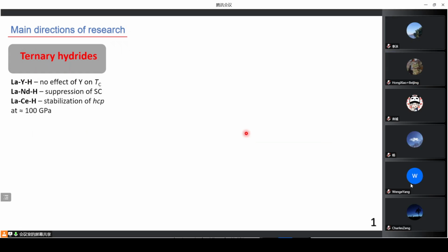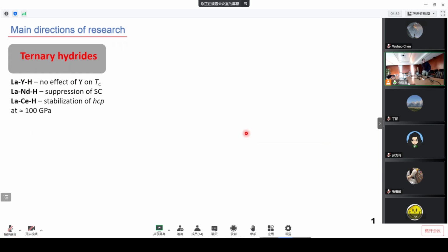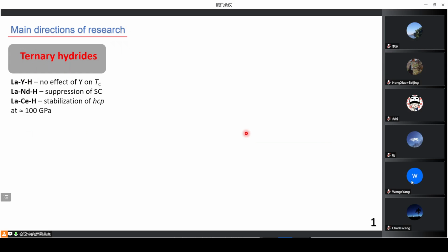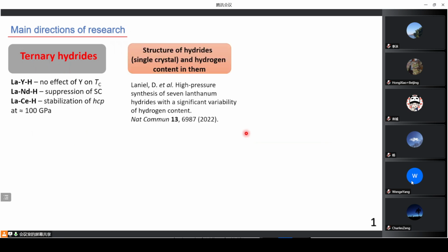And in the last system, lanthanum-cerium hydrides, my colleagues from Jilin University found that we can get some benefit in stabilization pressure. Stabilization pressure can be decreased because of formation of a new hexagonal phase. But unfortunately, the critical temperature also decreased, and actually, we are going down with this system from 250, which is TC for lanthanum H10, to about 180, which is the maximum TC achieved for lanthanum-cerium hydrides.